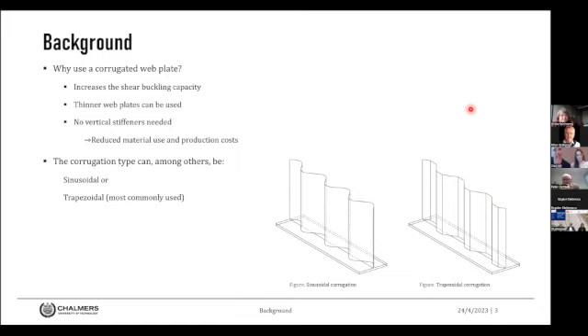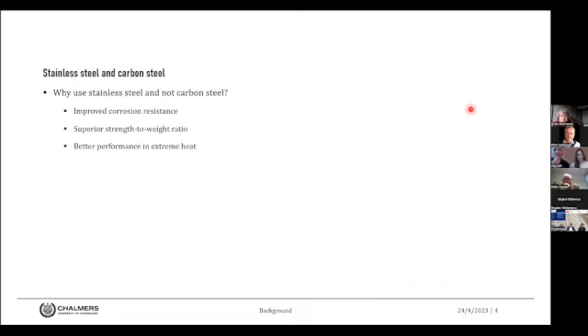Yes, so as known for most of you, I would presume, stainless steel has the characteristic of a stronger nonlinearity compared to carbon steel, and somewhat lower stiffness, Young's modulus. So for carbon steel, it's 210 gigapascal, and stainless steel, it's around 200 gigapascal. But of course, we could see that a much higher strength was obtained when changing to stainless steel, and that's due to the much higher yield limit, of course.